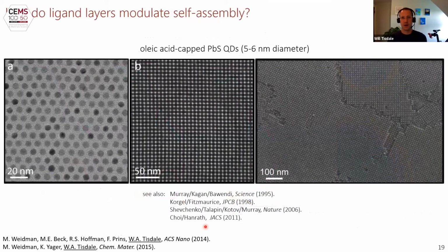Okay. Monodisperse quantum dots do a lot of great things electronically. They also will self-organize themselves into ordered structures. All of these images right here are just spin-cast batches of quantum dots where we let the solvent dry. This is not a slow, controlled crystallization. The quantum dots are self-arranging themselves like this in just a matter of seconds during the spin coating process. This is a TEM image looking down the 100 zone axis of a body-centered cubic superlattice. And this is the same material viewed in SEM.